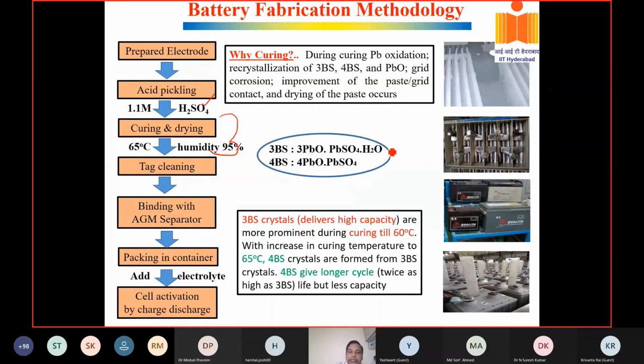Below 60, the paste will be 3BS. It's called 3PbO·PbSO4·H2O. This delivers high capacity but less cycle life. The other has more cycle life, a little less capacity. This is formed at greater than 65, about 65 to 70 degrees centigrade. Your temperature should not go beyond this. Most of the battery industry prefers 4BS generally, so they do the curing at 65 degrees centigrade, and this also takes around 24 hours.